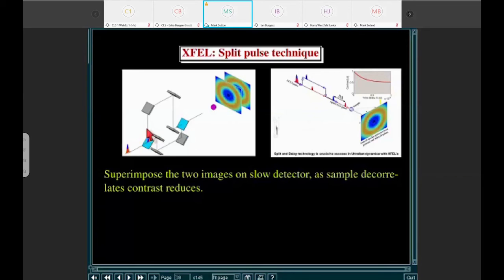So we've proposed to use a split X-ray pulse technology, where you basically split the pulse of X-rays into two parts. You time delay one with respect to the other. You let the first pulse scatter off the sample, and you get a speckle pattern, and the delayed pulse scatters off it as well. You shine the two speckle patterns on the same detector, so you can use a slow detector, and you can separate the pulses from basically femtoseconds up to nanoseconds, and so you can get time constants on that.